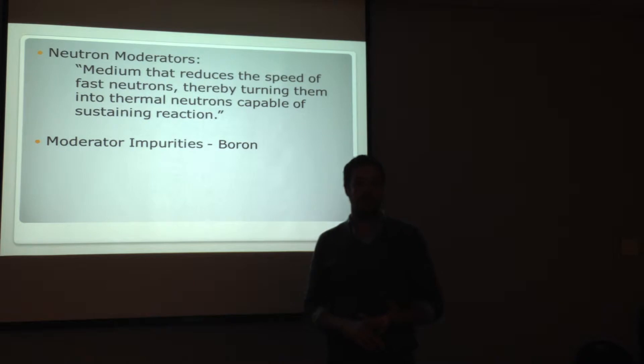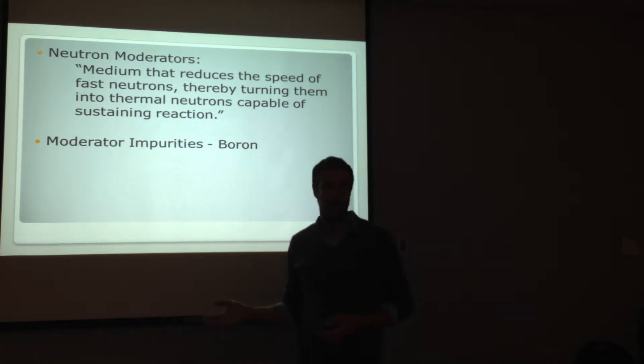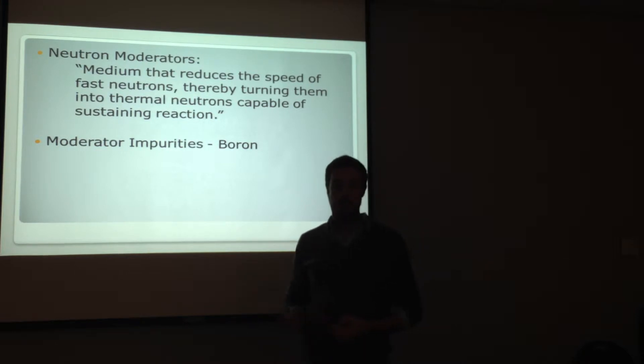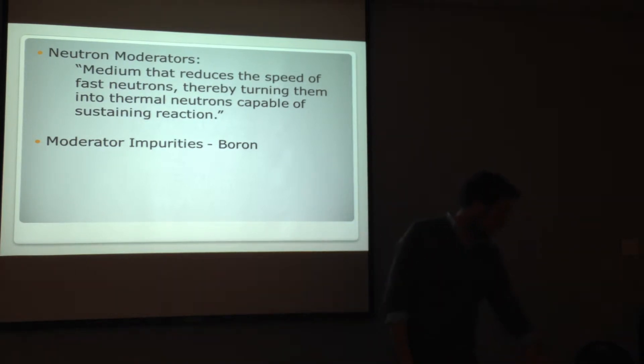Boric acid is corrosive, but in the case of pressurized water reactors it's inside the primary system and only comes in contact with stainless steel which is not subject to corrosion by boric acid. So, for boric acid to be introduced to the atmosphere and to be introduced to components that are corrosive to it, we'll talk about how that happened.